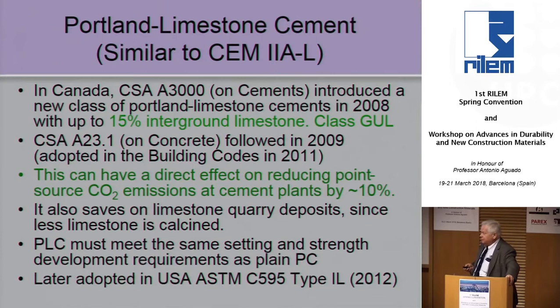ago into the Canadian standard with up to 15% interground limestone cement. So it's similar to a CEM II/A-L in the EN standards. There were a lot of reasons for doing that, and of course the cement industry in North America is largely European owned. You've got Holcim Lafarge, you've got Heidelberg Cement, and they had interest in bringing this technology into North America, and they used Canada as their first stop. It's now moved into the United States through ASTM more recently. But we adopted this first, and we designed these cements to have the same strength development, setting time and strength development properties as regular Portland cement.